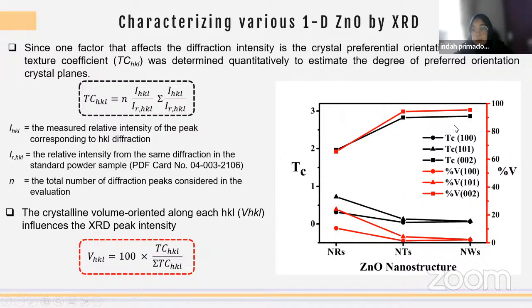And the volume is also the same for 002. The volume of the nanowire for the 002 plane is also the highest compared with 100 and 101. So I just want to show you with this formula that we can also compare the preferential orientation of the crystals of several materials. You also can use this formula.